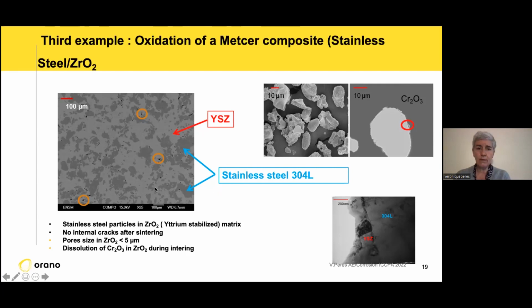And it was very interesting to see that if you look closely at the interface between the stainless steel particle and the zirconia, it's very clear, there is no oxidation layer, which typically appears with stainless steel powder. So all the chromium oxide present at the surface of this stainless steel is dissolved in the zirconia.